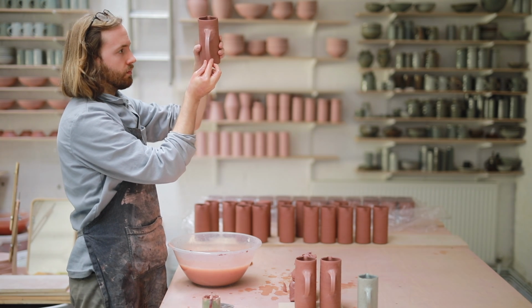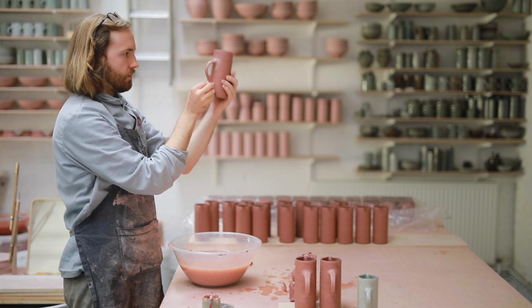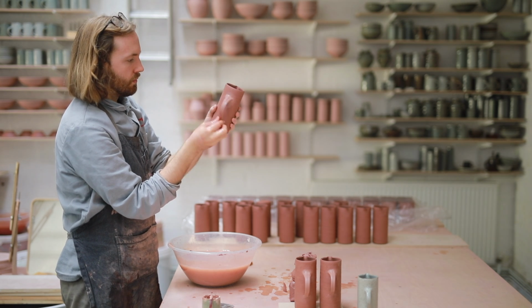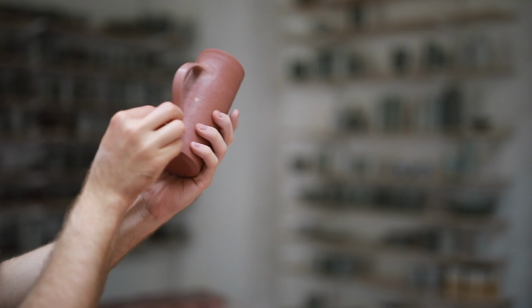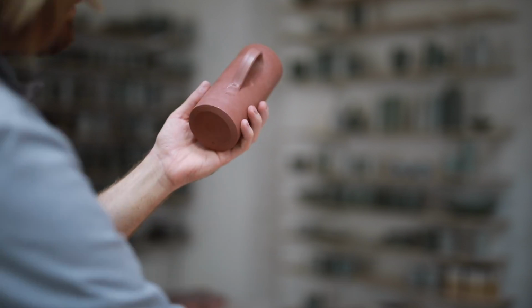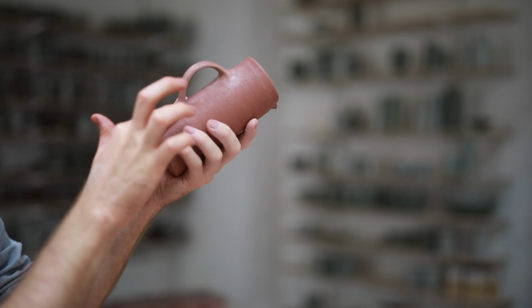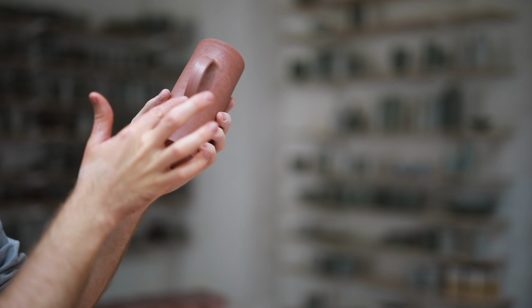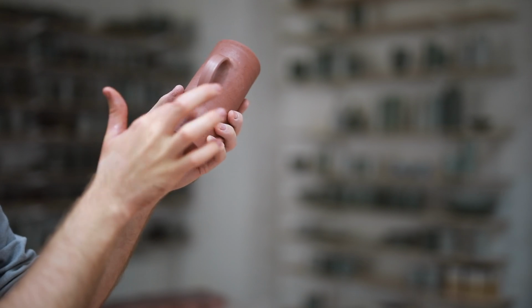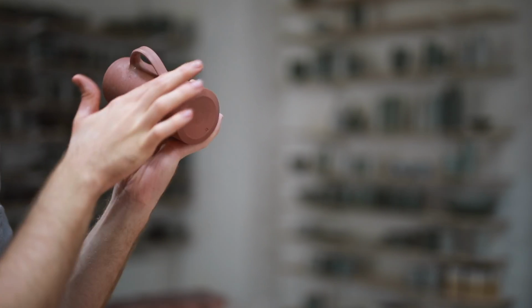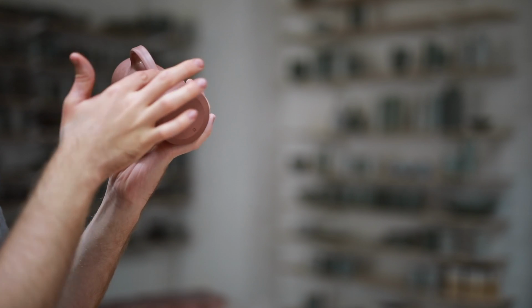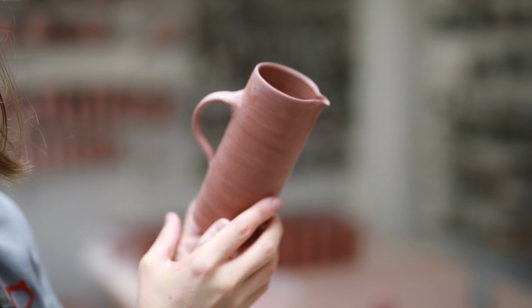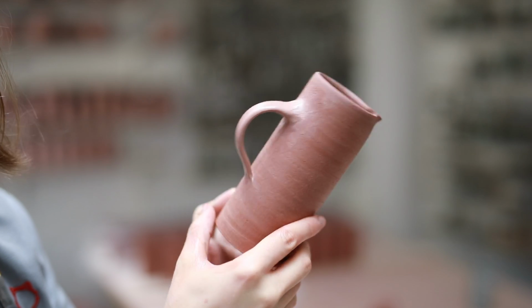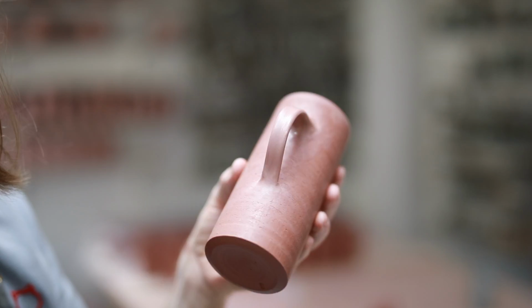I then angle the clay downward, make sure it's nice and straight, especially in relation to the spout on the opposite side. I then snip away the excess before blending it in, which is first done with just a dry finger, before moving on to a wetted finger to smooth over all my finger marks. At this point the handles are still incredibly wet, so I'll leave them a little bit before I move on to the next step, which is just one final quick cleanup of the base.